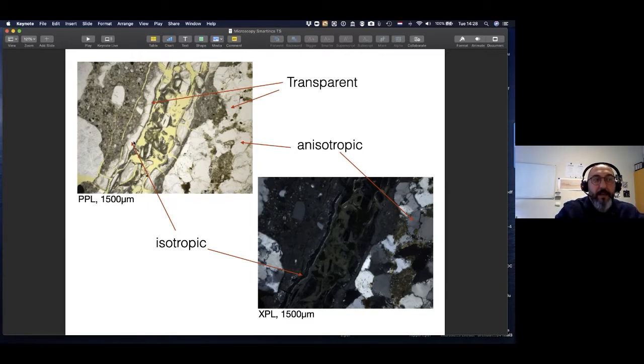a glassy microstructure, so it should give me isotropic features. And the only way, again, is to do this by testing optically, by going to the crossed polarized light mode in my microscope, by just inserting that secondary polarizing filter, and then I see everything super dark, you see? So if this is completely dark, it tells me that this is not a crystalline deposit, it is an amorphous deposit, which lets me tick one more box to identify it as an ASR gel.